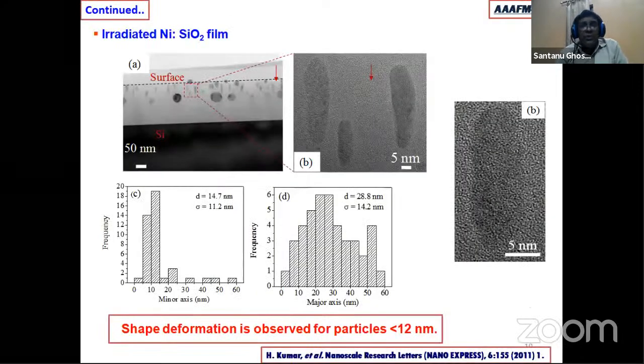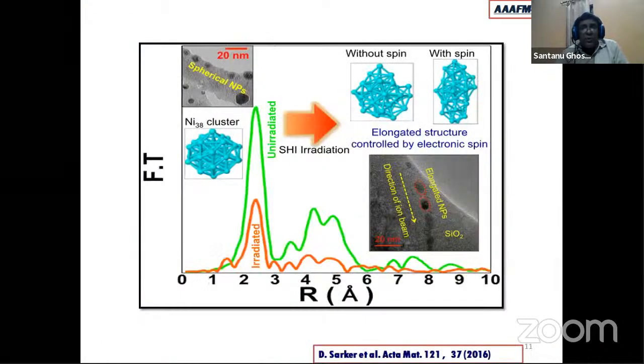The same thing we observe in transmission electron microscopy: after irradiation, the particles are all elongated. So we call them shape engineered nanoparticles. One can engineer the shape by changing the irradiation fluence. From the electronic structure point of view, the EXAFS results also show that the EXAFS peak intensity decreases drastically after the irradiation, which indicates that there are a lot of defects in the system. And also from DFT calculation, it has been shown that the particle shape changes.